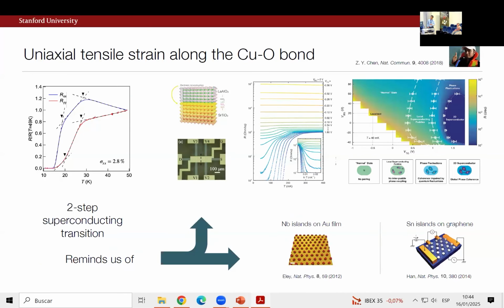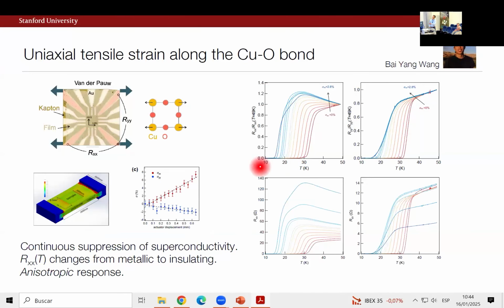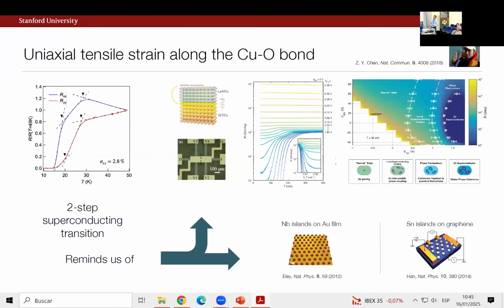Now, if we go back to this, clearly one qualitatively different thing is not just that we go from metallic-like to insulating-like in this case. You can see that TC is broadened out. We approach this 2-step transition. And actually, this is totally reversible. We can go back and forth on this. Okay.